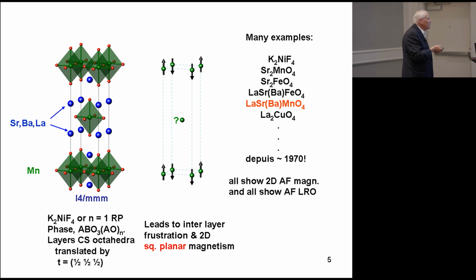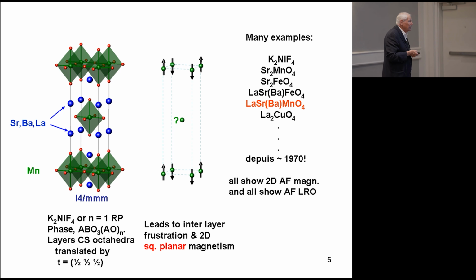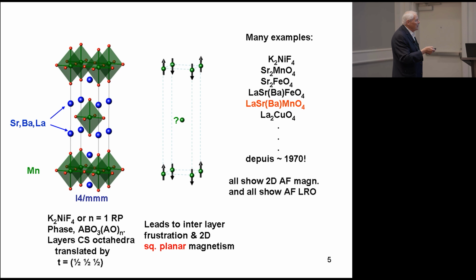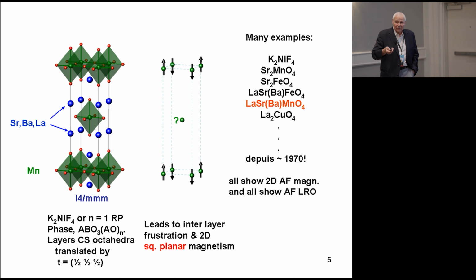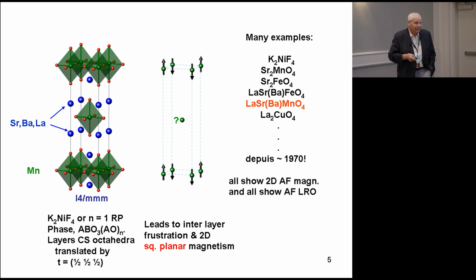Now, the source of interest in these materials, which are in the structure type also sometimes called the K2NiF4 structure, is the opportunity for low-dimensional magnetism, in this case, two-dimensional planar magnetism. As this little cartoon shows, if you have intraplanar antiferromagnetic nearest neighbor coupling, and you can see the configuration here, the layer in the middle of these two, the spins are actually frustrated, so you have 4 spins up and 4 spins down.